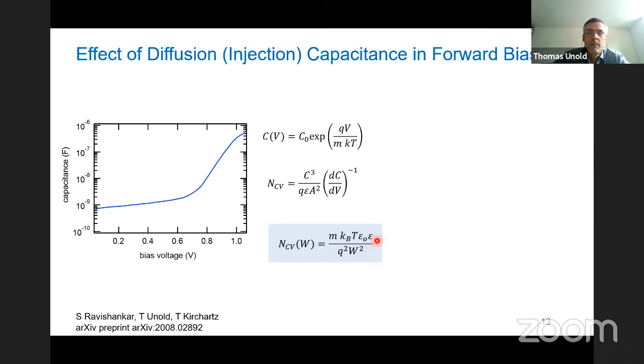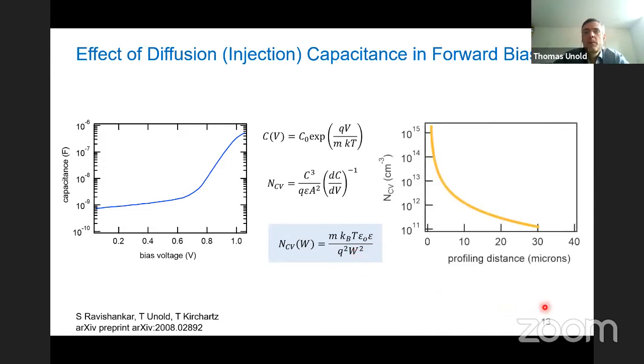So you get this CV charge density, or apparent charge density, and a relatively simple equation here. And it basically mostly only depends on the epsilon, that changes a little bit, not much, and then the square of the depletion width. So if I plot this, it would look like this. So you would expect something like this. This would be the CV density derived from this experiment, in this case. And if you plot it now over the profiling distance, it looks like this.